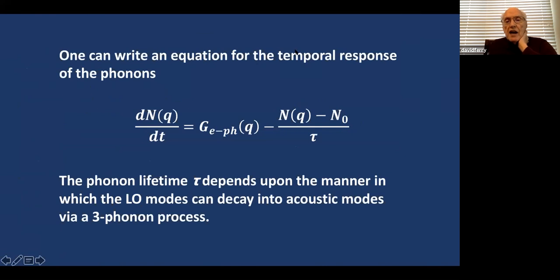Now we can write an equation for the time response of the phonons. Time rate of change of a phonon distribution is the generation rate from the electrons. So that's the net emission rate of the electrons emitting phonons into this mode. And we'll make this more exact a little later, but this is a relaxation of the real phonon from its equilibrium value with a lifetime. Now this phonon lifetime depends upon the manner in which the LO modes can decay into acoustic modes. And because you need to conserve energy when you're going from optical to acoustic, it's a minimum of 3 phonons involved. The one you're emitting and 2 more in the acoustic modes to take it up. So 3 phonon processes come from the 3rd order elastic constants of the material.